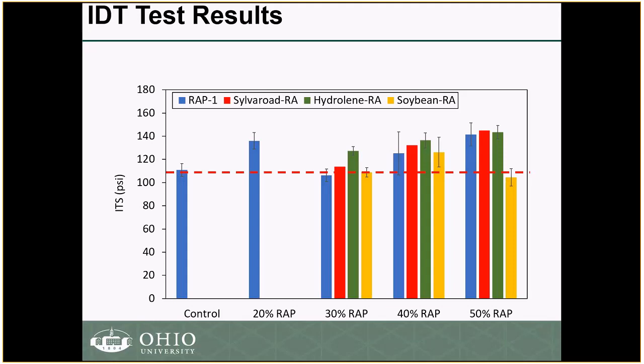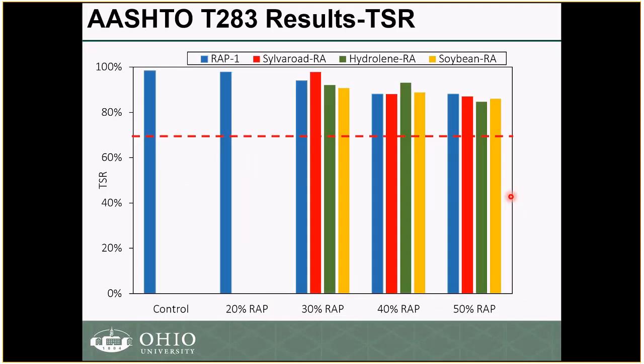And one of the things that we have noticed is that, in general, the different recycling agents did not really decrease the ITS, except, as you can see here, there was a little bit of a decrease with the soybean, and again, this is indicating a softening effect of that recycling agent.